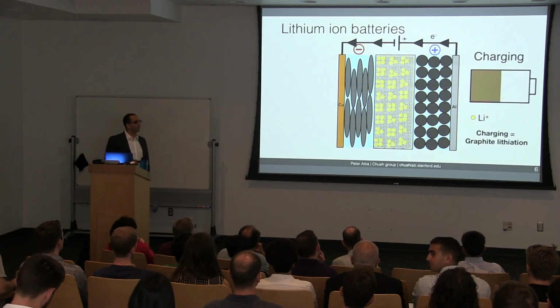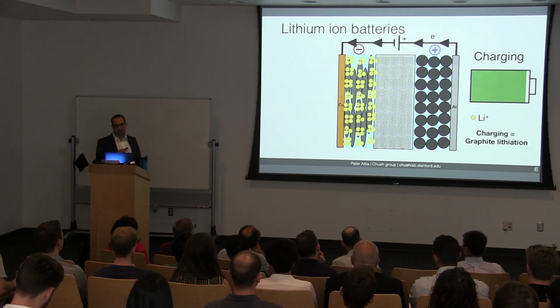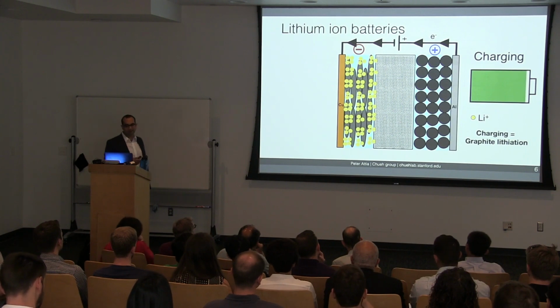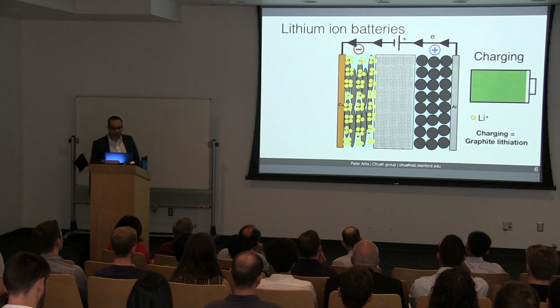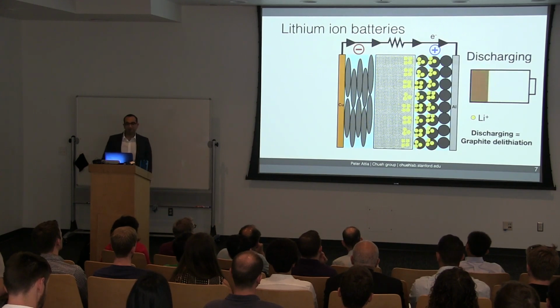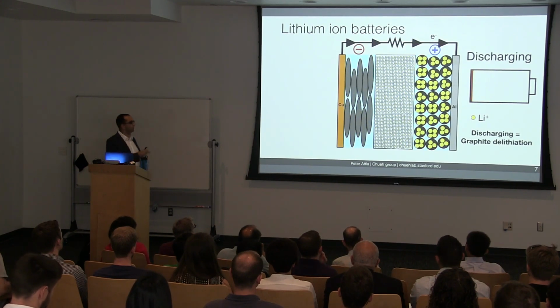So this is roughly how a battery works during charging. Both lithium ions and electrons move from the positive electrode to the negative electrode. So in studying graphite, the key thing to note here is that charging is graphite lithiation, or lithium insertion. And during discharging, the opposite happens. Both lithium ions and electrons move from the negative electrode to the positive electrode. Discharging is graphite delithiation, or lithium extraction.